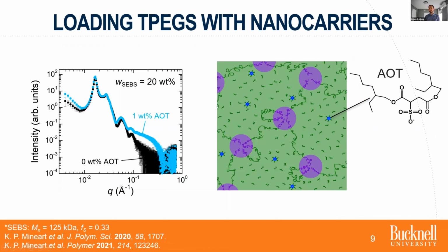As far as loading these materials, the kind of model probe that we selected to start off with is a molecule that's called aerosol OT. I'll refer to it as AOT. And the reason why we chose it is it's one of few well understood surfactants that form reverse micelles in aliphatic solvent. And so we really wanted to form some larger structures versus dispersed molecules in these gels to track diffusion of. And based on literature, we expect that we'll get small reverse micelles in our aliphatic mineral oil solvent.